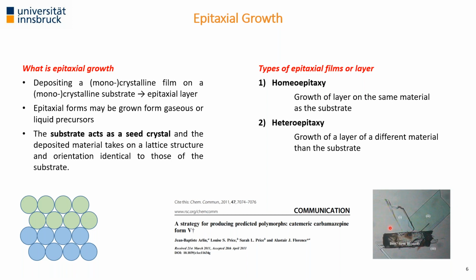What's special about this form 5 is that it is the first catemeric structure, because the previously known polymorphic forms were all dimeric structures. So that's one of the big successes and a really nice example that shows how you can use seed crystals of related molecules to produce new polymorphic forms, because those two compounds you can see near the crystals here, the crystal structures, are isostructural, as the sublimed material takes the lattice structure and orientation of the substrate. I would say that's a big opportunity to produce new polymorphs, seed crystals, which can then potentially be used in cooling crystallization experiments for upscaling.